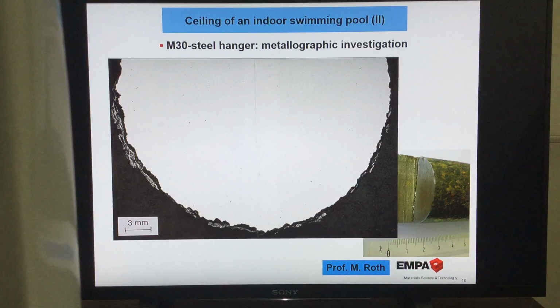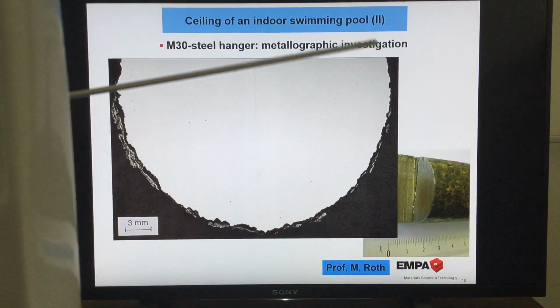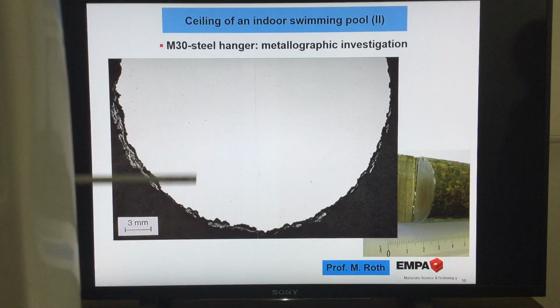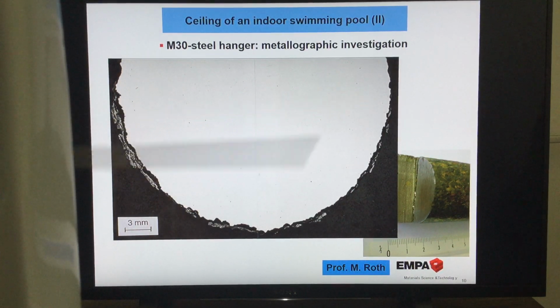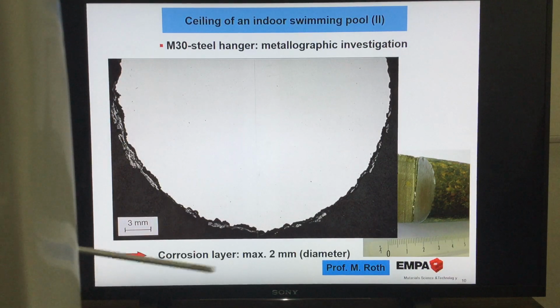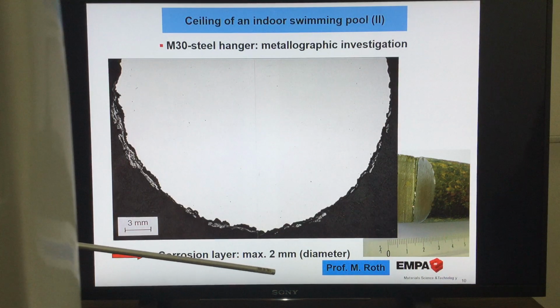So we can judge a little bit because it will be important now to calculate the stress in the rest of the diameter, because that oxide layer doesn't take over any load. So the stress will be higher because the diameter is reduced. The diameter, let us judge. When you watch at this, I think it's about here 1 millimeter, maybe here a little bit more. So totally we judge it's about in the diameter, the corrosion layer, maximum 2 millimeters, which will be reduced of the load-bearing area. Because again, the corrosion layer is just brittle, it falls apart, you can scratch it off, it's less.